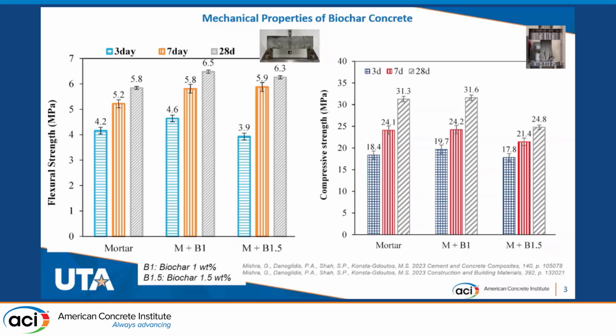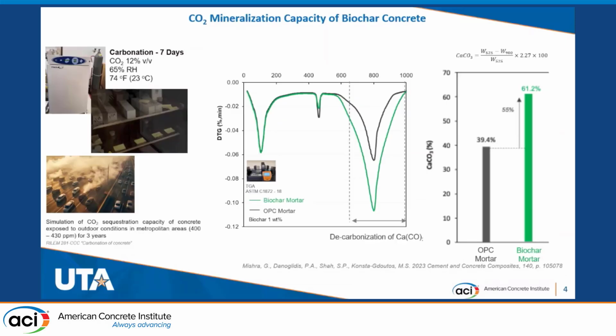The compressive strength values of the specimens are shown in the graph on the right part of the slide, and from the results we observe that mortars with 1% of biochar indeed exhibit a higher compressive strength. However, when we increase the dosage of biochar, the compressive strength decreases. So the 1.5% biochar mortars exhibit a reduced compressive strength. And this can be attributed to the porous structure of biochar, so a higher amount deteriorates the mechanical properties of the cementitious materials.